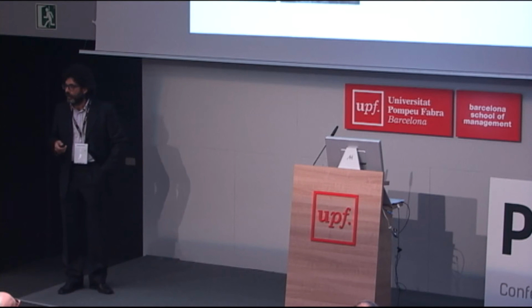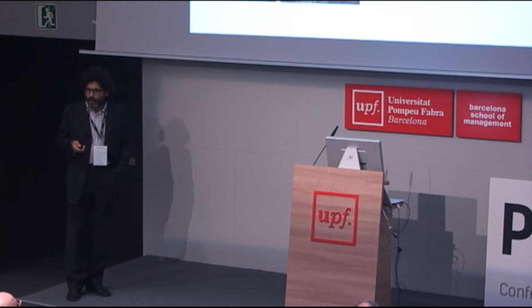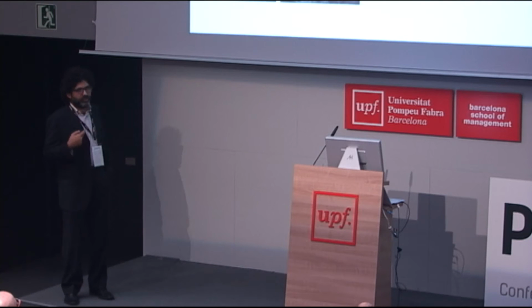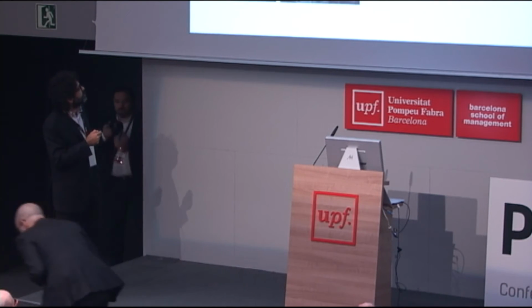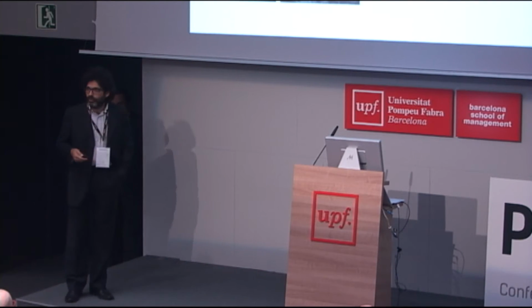Why didn't it work at higher concentration? First, one motivation is that carbon nanotubes and graphene are absorbing light which cannot be used for charge photogeneration. Secondly, because at higher concentration you have the formation of cracks in the film, which is no longer suitable for charge transport. We got the same with graphene nanosheets.